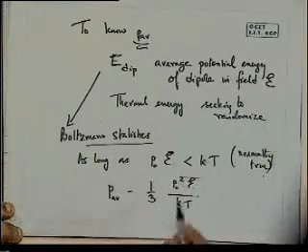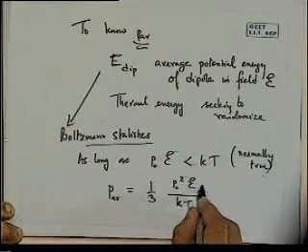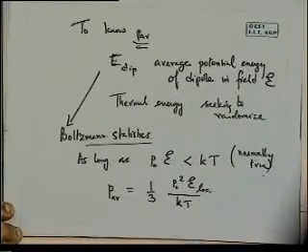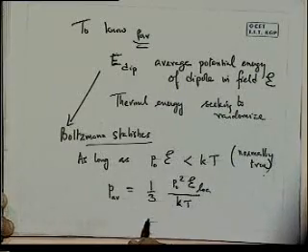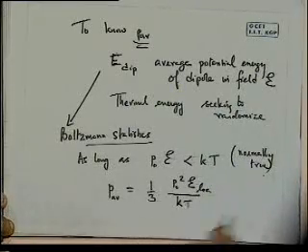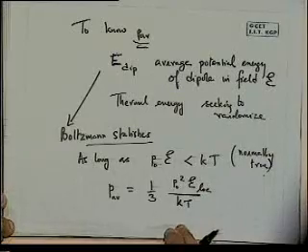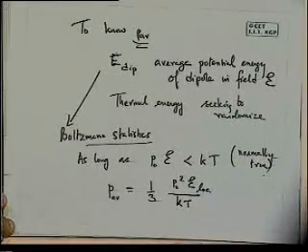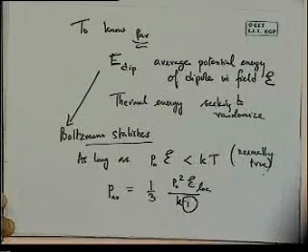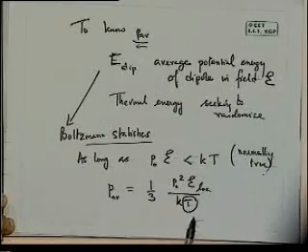Strictly speaking, if you want to be more accurate, you would use the local field idea, what the exact dipole is experiencing and not the simple average value. What we see here is that we've got a temperature dependence to this whole thing, which we did not have for the electronic polarization or for the ionic polarization. There is a T term here. And so orientational polarization is strongly temperature dependent, whereas the others were temperature independent.